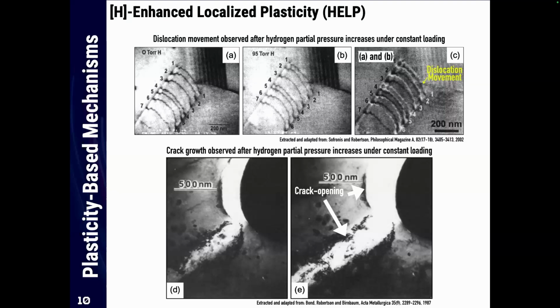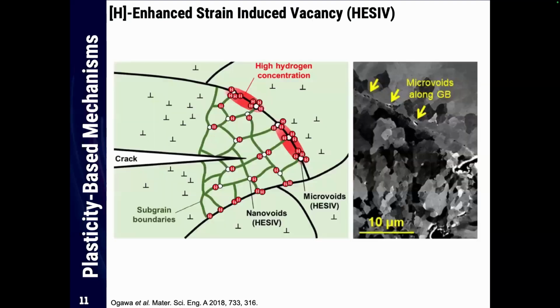They did the same for cracking. They did a crack in an aluminum alloy. And then after the insertion of hydrogen in the chamber under load, they observed that the crack opens, but there was no local measurement of hydrogen. It's a limitation. We have also another plasticity mechanism called HESIV, developed by Ogawa.